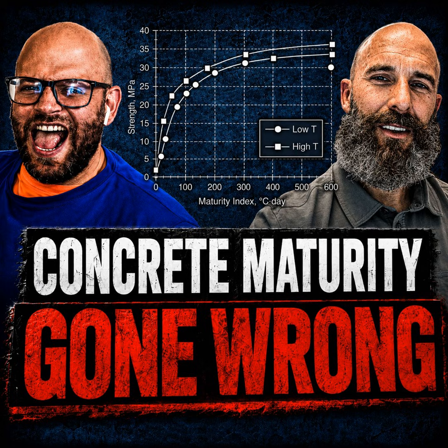So with that datum temperature, the reminder is it's the minimum temperature needed to kick off the kinetics of cement hydration. So if we assume the wrong datum temperature and we're trying to pull forms, we can assume, so we're starting at 0. I can assume a datum temperature that's way too low, negative 10 degrees Celsius, and way too high, plus 10 degrees Celsius. Remember, our actual was at 0.